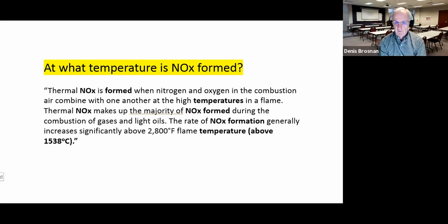So NOx, what temperature is NOx formed? And you can see that in this quote, NOx is formed above about 2,800 degrees Fahrenheit. That's about 1538 degrees Celsius. So most natural gas burners can produce NOx. It's not from the nitrogen in your product, primarily, but it's from the high temperature burners. One very practical way to look at this is if your kiln is fired above 2,800 degrees Fahrenheit, then you're going to have a situation where the air passing through the kiln can create NOx. Now we have low NOx burners today. Your burner supplier can help you reduce the NOx emissions, which in non-attainment areas in the United States is a very important thing in ceramic manufacturing.